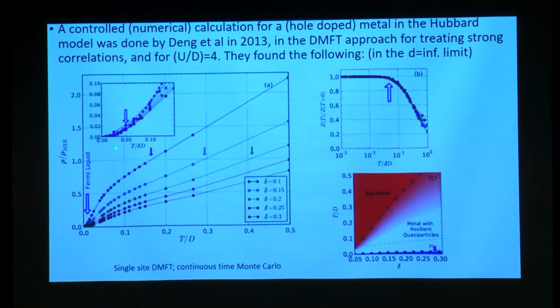If you blow up this part, you see that it increases quadratically with temperature. So their focus actually was on this crossover from the T-square regime for the resistivity to the T-linear regime, which crossover extends over a fairly wide range of temperatures. They showed, for instance, that in this regime, you do have well-defined quasi-particles. For instance, if you ask for the quasi-particle residue, you find that it has a value 1, which is perfect. But then it decreases dramatically to become very, very small. Now, this region they sort of identified with a crossover temperature.